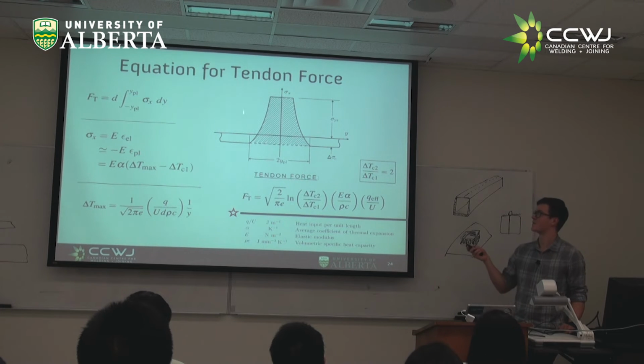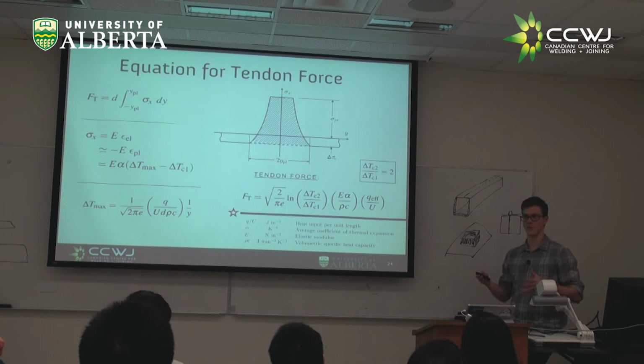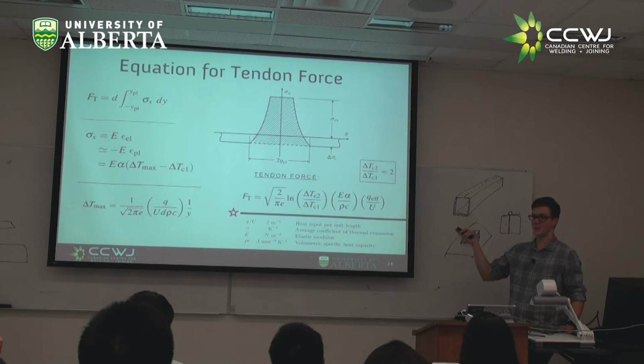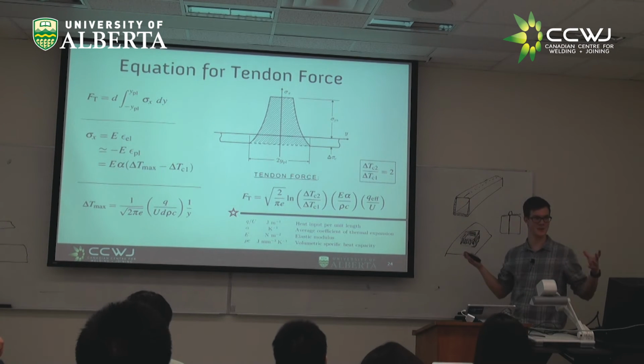I think this is one of the most powerful things you can learn about residual stresses. If there's only one thing you remember from this class, it's that a stronger material does not necessarily have more deformation, more net residual stresses. The individual magnitude of the residual stresses, the peak value of this curve, might be higher. But the integral, the total amount of stress you have to drive deformation, to drive stresses elsewhere, is not necessarily larger.